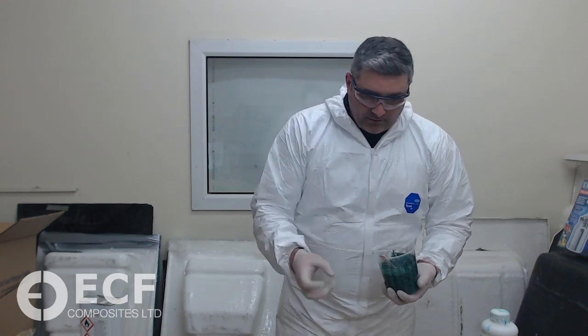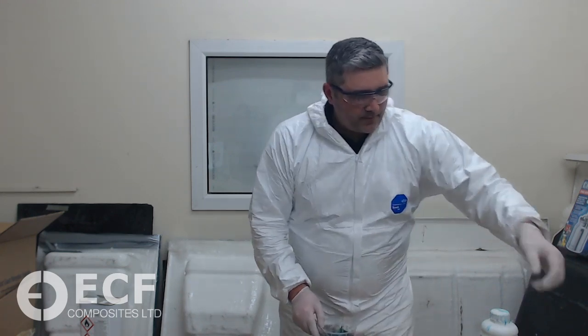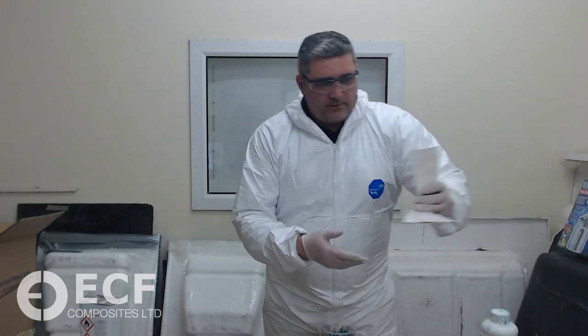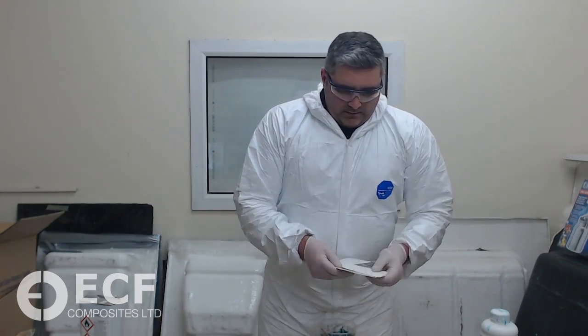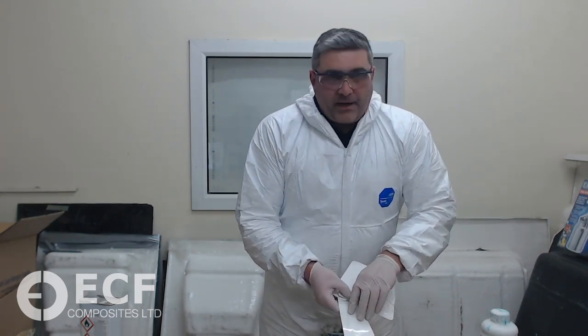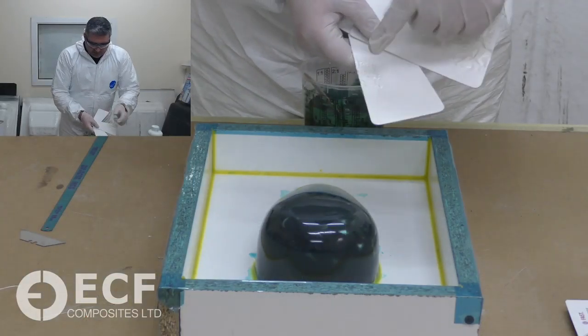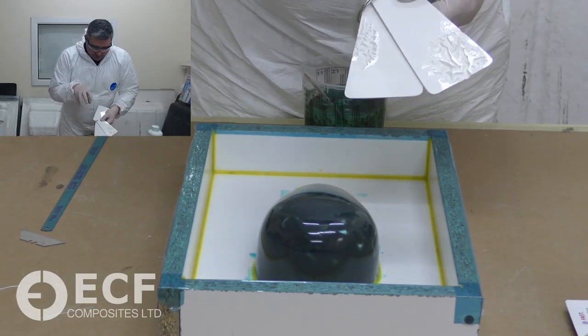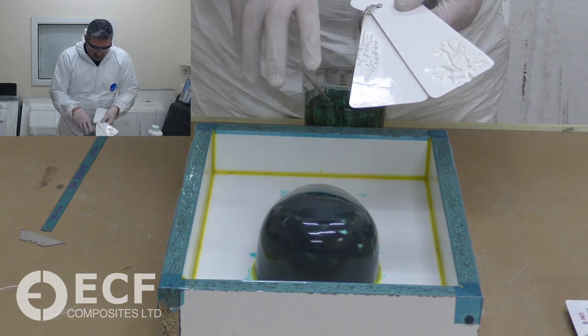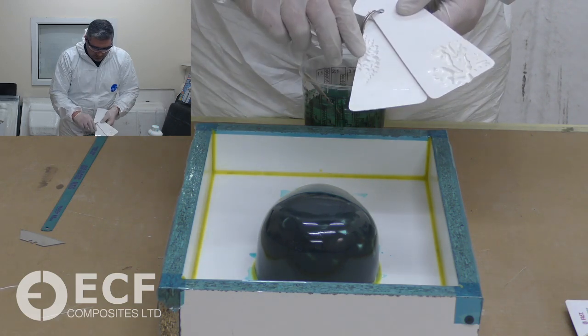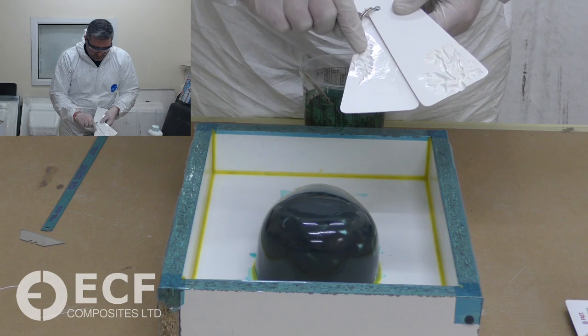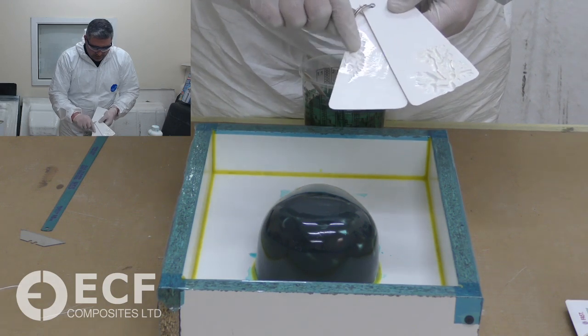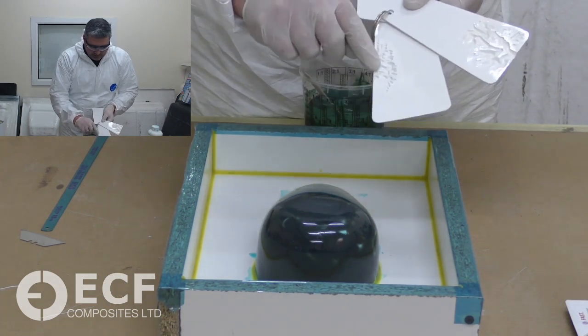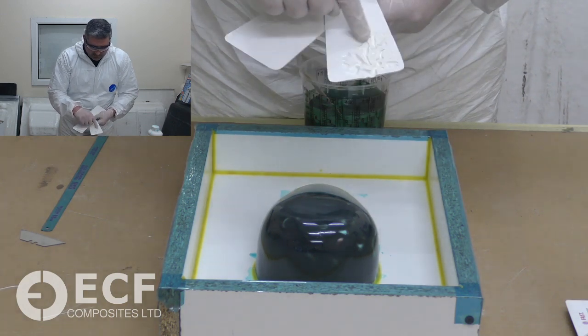And then when you pop your mould out, you get all these little crinkles everywhere. I've got an example here. It's known as wrinkling of the gel coat, and it's basically just exactly what it does. The resin takes too long to cure off because of the cold temperatures, and you get these little crinkle lines on there. It's actually a normal case, that's the most severe case on there.